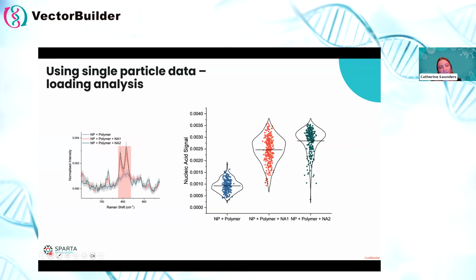So this is where I look at the nucleic acid signal, and I'm going to compare an unloaded control to the two loading conditions. So what you'll see on this univariate plot is that there are all of these dots. Each one of these represents an individual particle that was measured. And the higher the dot is on the y-axis, the more of this nucleic acid loading signal that we're detecting. So basically, the higher the loading, the higher it is on the y-axis.